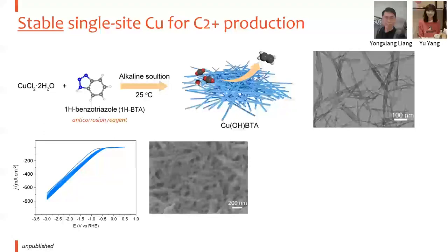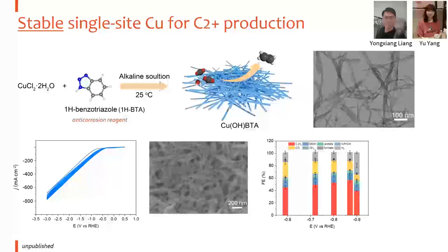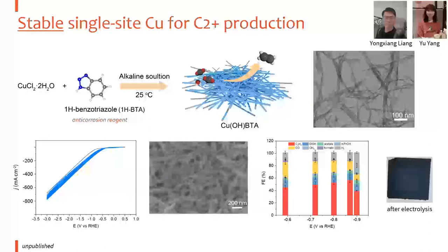And we checked the SEM image of the catalyst after reaction, and we found that the nanowire morphology remains. And we analyzed the product for the CO2 reduction using this material, and indeed we observed quite a number of C2 products with high selectivity. And even after the reaction, if we check the color of the catalyst, it remains dark blue. If you are working with copper, you know that copper usually shows a reddish color. So if you reduce the material to form copper nanoparticles, it was expected that you will generate some reddish color. So it's kind of stable if we just use our bare eyes to look, but we want to characterize the material and the operating condition to see whether it's really stable during working conditions.